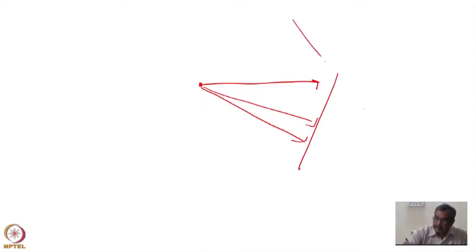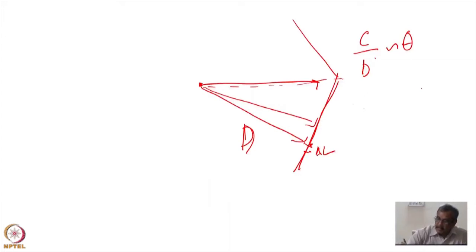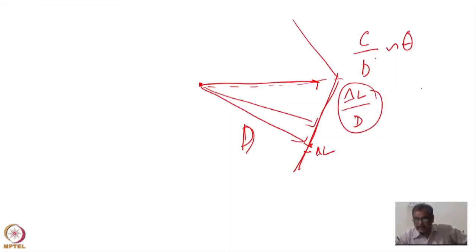So here, as I showed, there is a sample from which the neutron beam is scattered and goes in various directions, and we have position sensitive detectors, the bank that I showed you. If the distance is d and the position resolution is delta l, then knowing the average position, the channel number divided by d will give you an idea of theta, and delta l by d will give you the resolution, delta theta, of the setup.